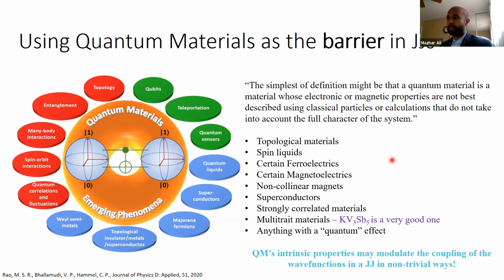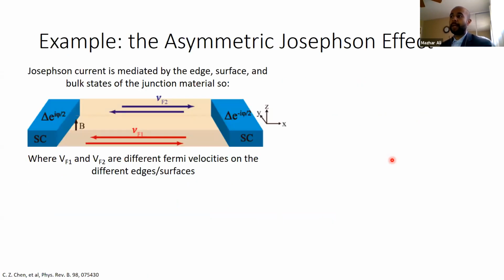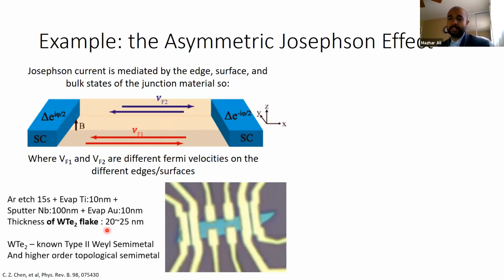So this is not just pure pie in the sky stuff. For example, this has been seen at least once already in what's known as the asymmetric Josephson effect. The idea there was that you have, again, your two superconductors and a barrier material in between that was a topological material. So it had edge or surface states or hinge states, whatever, as well as the bulk states. And the superconductivity across this barrier is mediated by all the metallic states available, including those edges and surfaces. Now, if you happen to be breaking inversion symmetry, then it's possible that you unlock, let's say, the top and bottom surfaces in terms of having the same Fermi velocities. It's no longer required. Now, exactly this scenario was seen in one of my favorite materials, tungsten ditelluride.